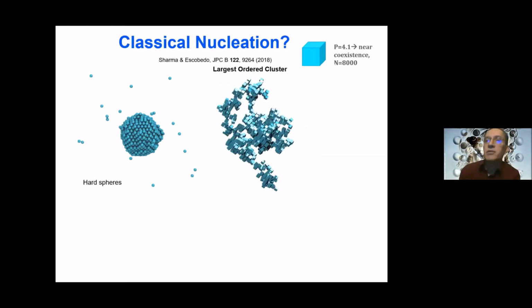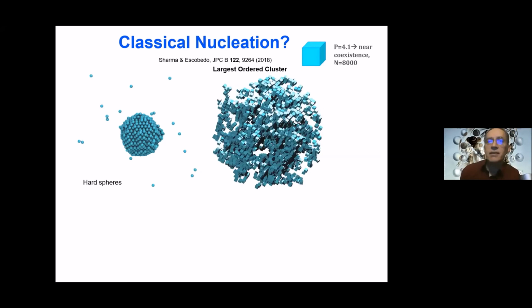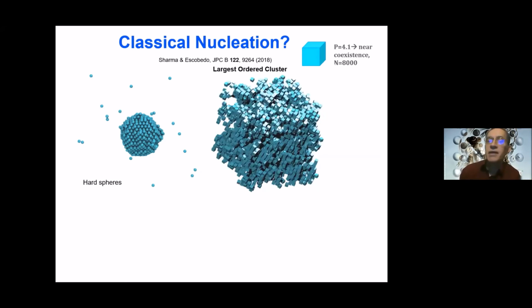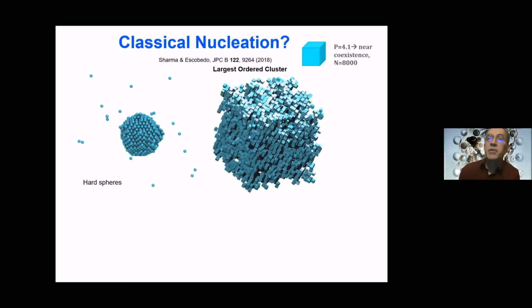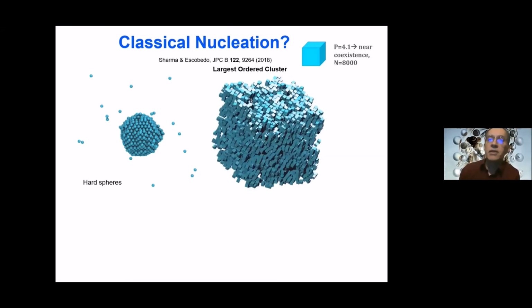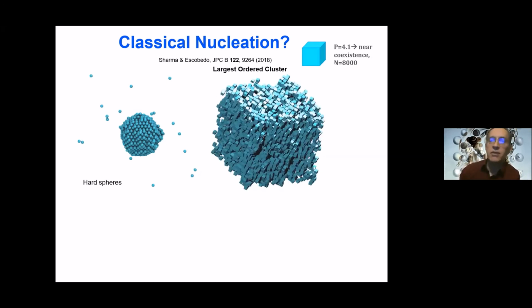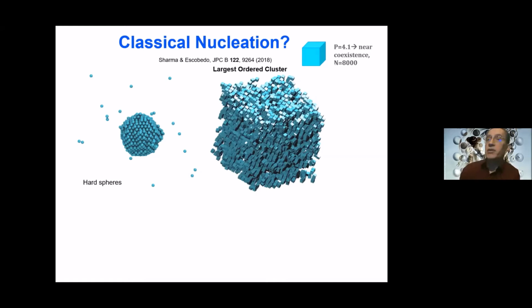So there I'm trying to just plot the largest cluster, and the largest cluster just comes and goes, doesn't stay put. And we believe that connects to this low interfacial free energy that allows them to dissolve very quickly. But at some point, there are enough of them that they percolate and form this sort of one-phase behavior.